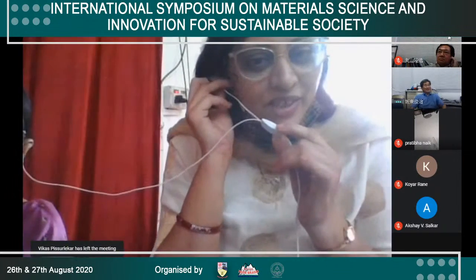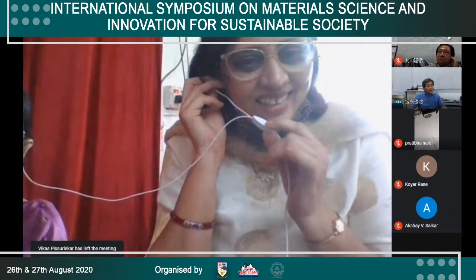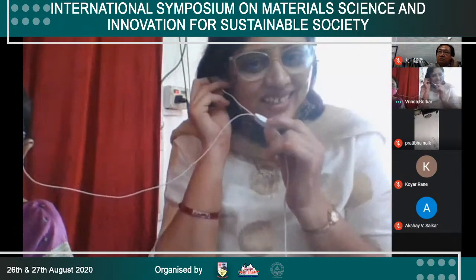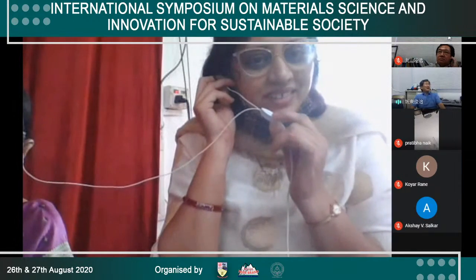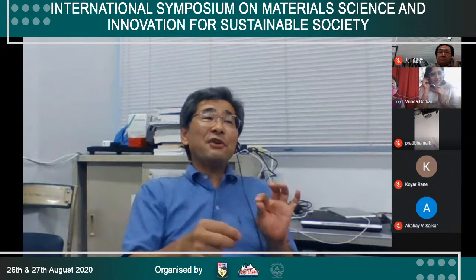Okay, and what is the resistivity of that wire? Resistivity of the nanowire. Normally the MoS2 is insulating. So when some molecules are attached in the nanotube and charge transfer occurs, in such a case, the MoS2 electric feature will change and the electric resistance or conductivity changes, I think. It should be, or possibly can be, used for some gas sensor or such kind of application.